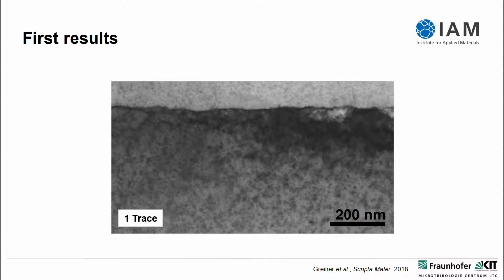If you use high-resolution TEM—results I'm not showing today—and really zoom in, you see that this line is a structure made out of dislocations. That's why we call it the dislocation trace line. It's really the self-organization of dislocations in the stress field of the moving sphere. I will show you a first idea of how this might happen in a second.